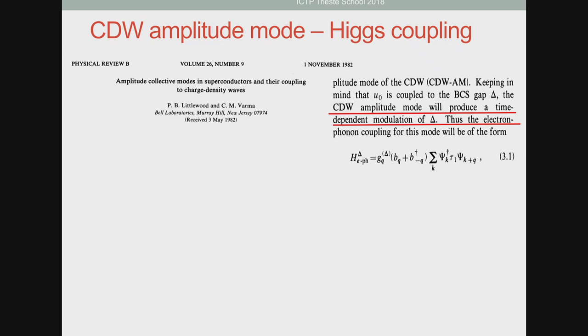The scenario that was put forward was that there is actually a coupling between the amplitude mode of the charge density wave phase and the amplitude mode of the superconducting phase, in other words, the Higgs mode. And this was the scenario proposed by Littlewood and Varma. This is a PRB paper of 1982, quite soon after the first experimental measurements. What they propose here, I'm extracting an excerpt from this paper, keeping in mind that U0 is the lattice distortion associated to the charge density wave mode, coupled to the BCS gap.